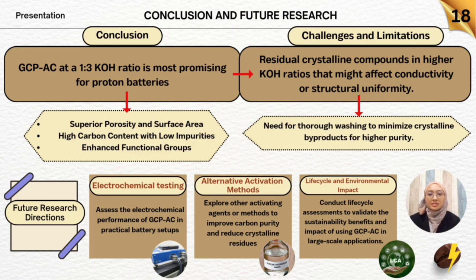One challenge that we found is that residual crystalline compounds, especially in the 1 to 4 sample, could affect conductivity and structural uniformity. The solution is that enhancing post-activation washing could reduce these residues, resulting in a more amorphous, impurity-free structure. Future research includes conducting electrochemical tests to validate this material's performance in real battery setups.